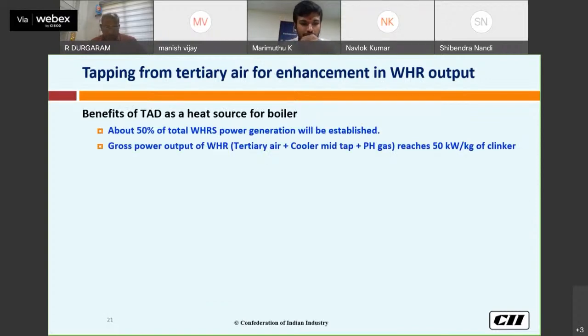Then the benefits: for example, if we are able to produce 10 megawatt from WHR with the TAD, we can produce around 50% of total WHR. The gross output from the WHR, combining tertiary air, cooler mid tap and PH gas, can reach up to 50. The best figure we have seen is around 43, and the average we have seen is 35. So by adopting this one, we can achieve up to 50 kilowatt per kg of clinker.